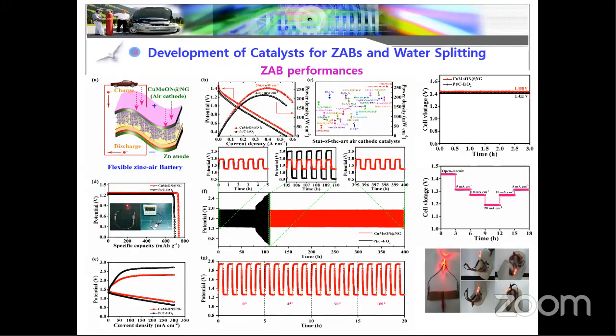Yes, in the presence of oxygen, zinc normally has a tendency to dry. But on the zinc side we are not using air; only the cathode side uses air. Still, the electrolyte is very important. Gel electrolyte fabrication is one of the challenges. When fabricating the gel electrolyte, the composition should be perfect. Then the zinc never dries. Otherwise, the electrolyte may dry, may be rotten, or may not be flexible, and then this problem will happen.